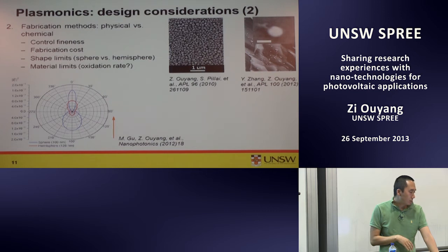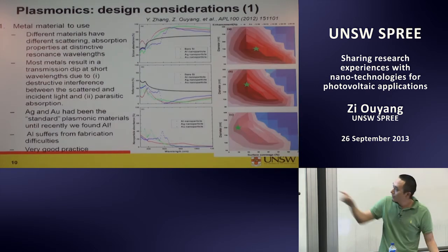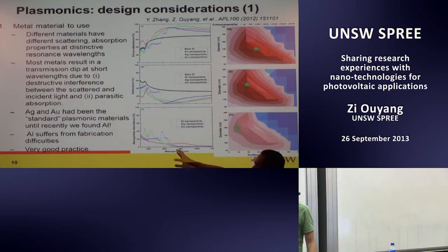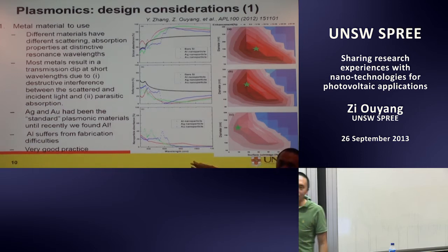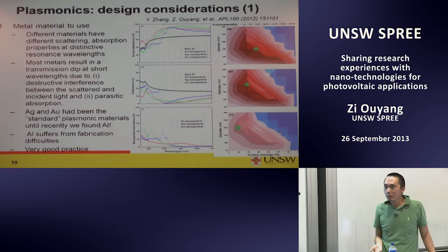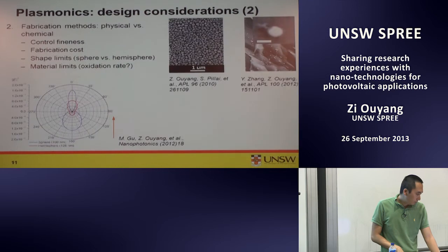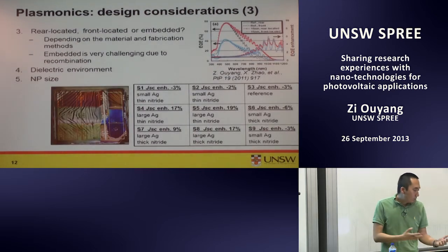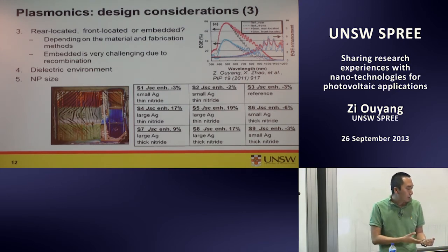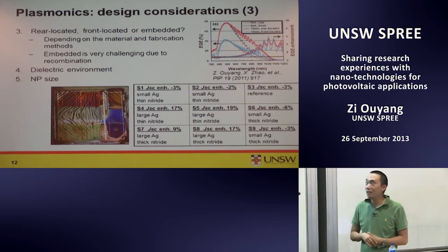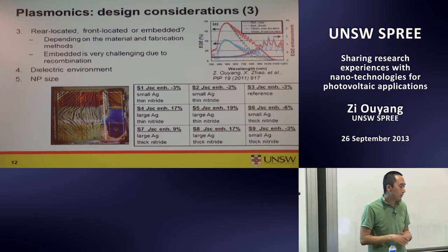So material limit, I just talked about that. Aluminum is very good, but its oxidization rate is very high. And if you look at this curve, the underneath one, you will find the absorption of aluminum is better below 600, but actually absorption is higher at the long wavelengths. So probably aluminum is not a proper material for the BSR application. Then you want to put it on the rear side, the front side, or embedded inside. That depends on your cell design. But usually, for the embedded configuration, I never heard of anyone getting any efficiency or performance improvement. Simply, you put the metal in a bulk material. That sounds terrible.